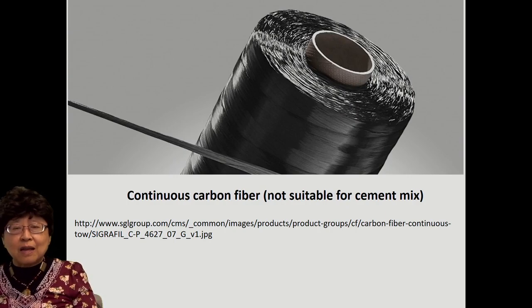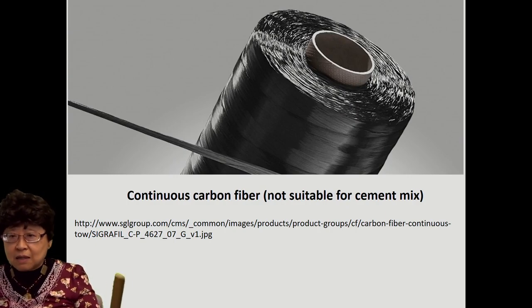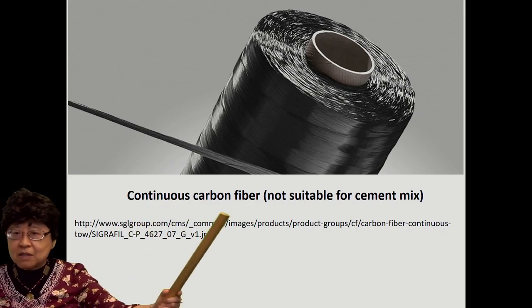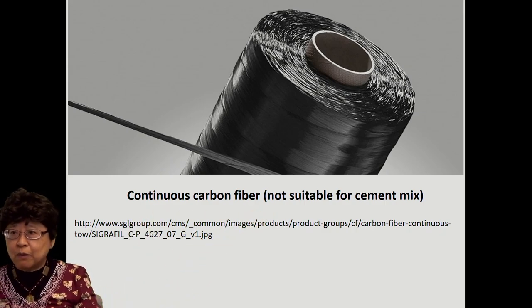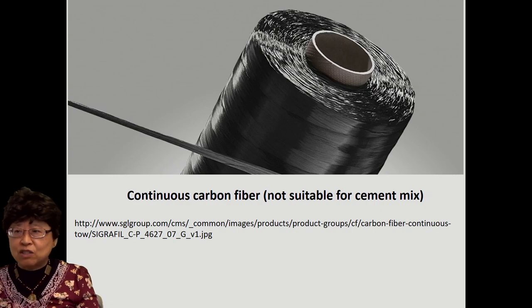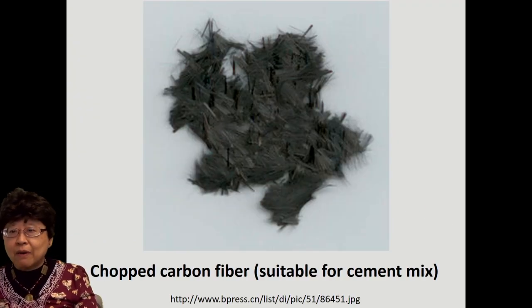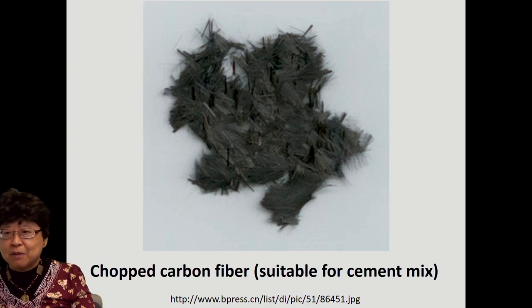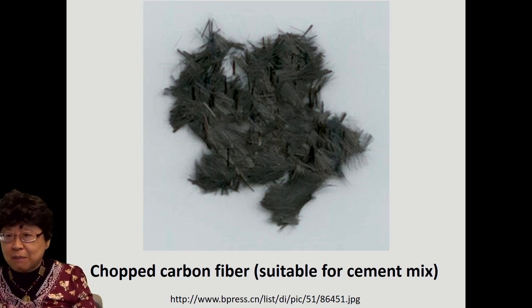Now, the fibers that I use in the cement are not continuous fibers, because continuous ones are not suitable for incorporation into the cement mix. Rather, I use the chopped carbon fibers, which can be thrown into the cement mix.